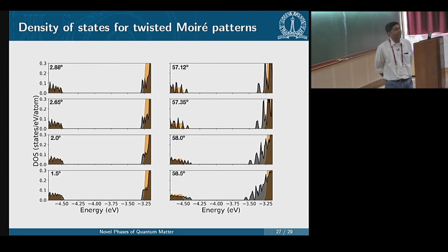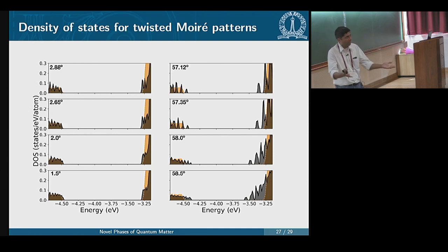Okay, so energetically stable meaning, we have calculated phonon spectra for these. What we find is that at angles close to 0, in the phonon spectra there are no negative frequencies, barring some bending mode related things, which you can double the cell and get rid of. Near 60 degrees, an angle which is much smaller than 1.5, actually 1.5 seems to be the threshold below which there's a lattice reconstruction. Lattice reconstruction at the Moiré length scale. I think Indrajit had a poster about this outside. But once you do the reconstruction, you can find a structure which is stable.